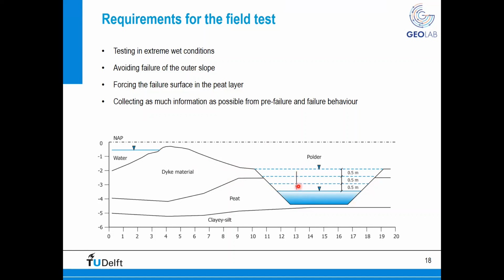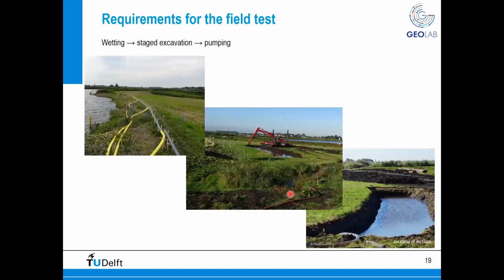So we were able to perform a series of drawdowns: the water is lowered, then we refill it, then we lower it again, refill it, and lower it again. In such a way, we were able to collect information throughout different stages of the test. Now, in order to collect information, we designed this test. You see here the wetting system that we placed at the top of the dyke in order to test the material in wet conditions, which are the most critical for the Netherlands. Here you see an impression of the excavation of the toe of the dyke. And here you see one of the stages of the dewatering. So we were lowering the water table inside the excavated area at the toe of the dyke.